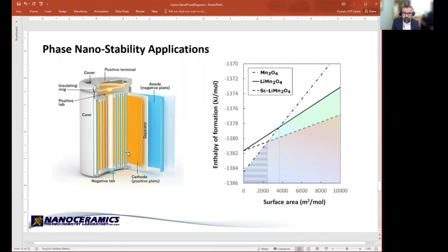Think about it, the lithiation and delithiation process depends on how much surface area I have in the system. The more surface area I have, the more ionic exchange I can have, so lithium can go in and out quicker. So nanomaterials are known to be a better option for batteries. The problem is that there are concerns about phase stability, coarsening, cracking, and reactivity.